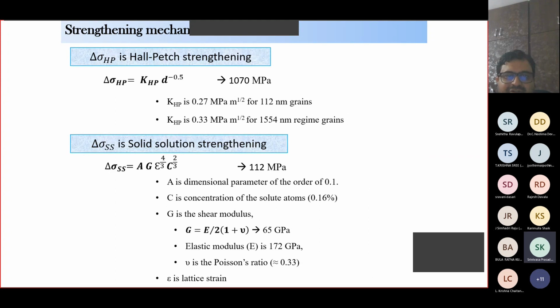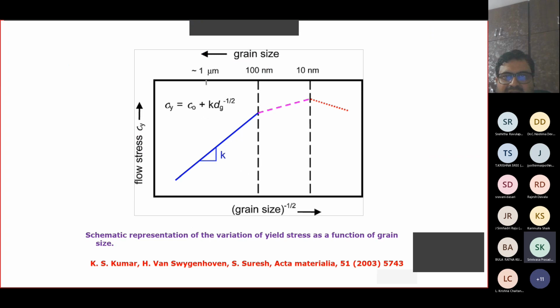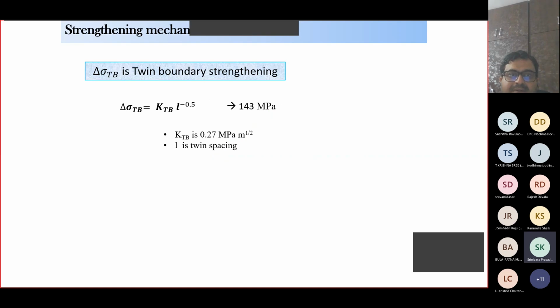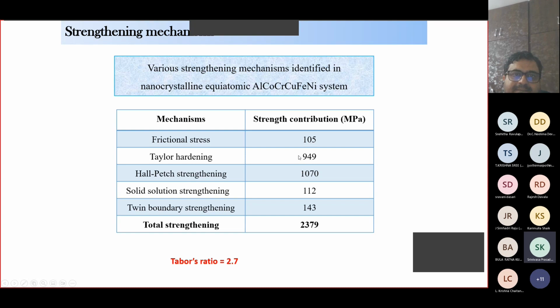Hall-Petch strengthening, solid solution strengthening, and also I have discussed this figure in the beginning of this lecture, that at different grain size regimes you have different Hall-Petch constants, and you need to consider those. And here twin boundaries also govern the mechanics of plasticity in a way the grain boundaries influence. Therefore, Hall-Petch type of dependence, that is 1 over root d, is also assumed here for the twin boundary strengthening as well, and it works very well.